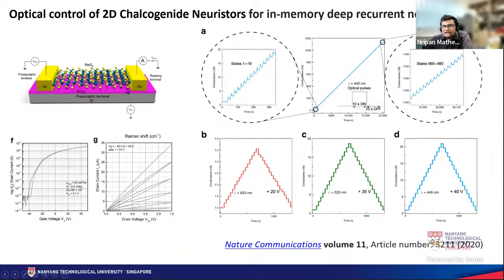So we showed that the conductance level of this kind of transistor can be controlled by light, with about 980 states. We also showed that you can increase the conductance with light, and then erase it by applying a voltage. And we also showed the sensitivity of this material to different wavelengths, which could be utilized, for example, for selective control of one synapse while not actively controlling another device, etc. If you are interested, you can read the details in this particular paper.